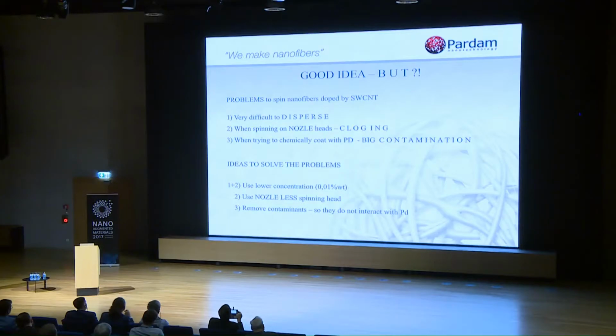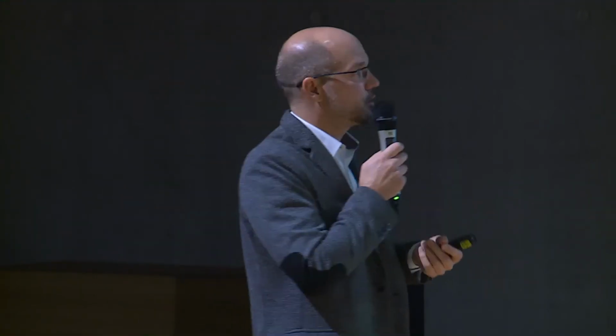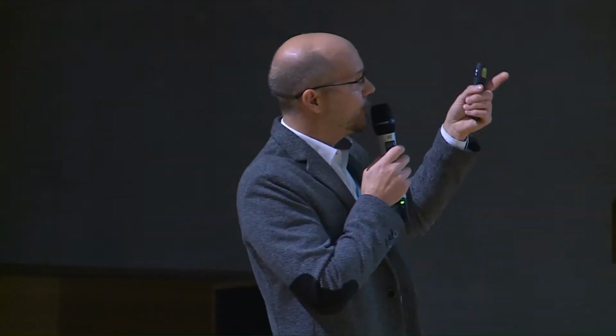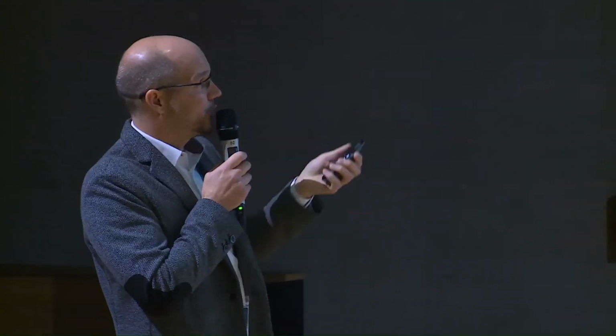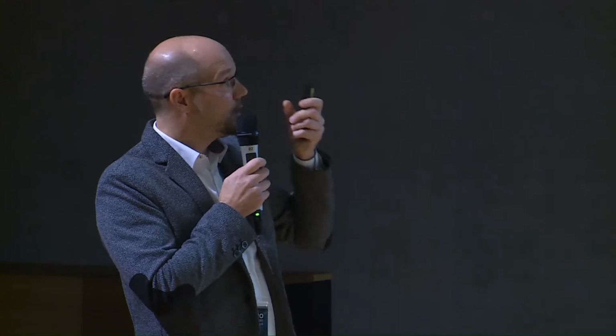The problems we have observed: the nanotubes were very difficult to disperse. It's a general problem with single-wall carbon nanotubes, so there is a process which needs to be optimized. When spinning on nozzle heads, it's clogging. And when trying to chemically coat, I was speaking to the partners from the university. They found quite big contamination of the single-wall carbon nanotubes by different catalysts.